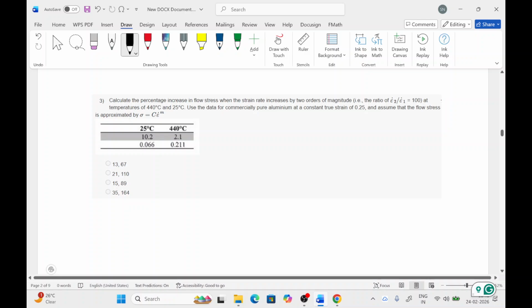Next question we have asked: calculate the percentage increase in flow stress when the strain rate increases by two orders of magnitude, meaning epsilon-2 dot by epsilon-1 dot is 100, at temperatures of 440 and 25 degrees Celsius. Use the data for commercially pure aluminum at a constant true strain of 0.25, and assume that the flow stress is approximated by this equation. Here we have given this is C and this is M. We have been given the values of C and M at two temperatures, and also the strain rate ratio. We just have to find by what percentage the flow stress increased.